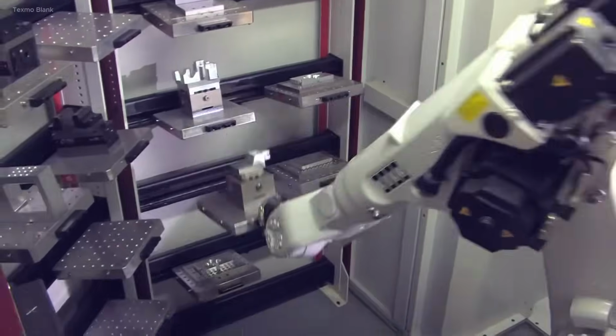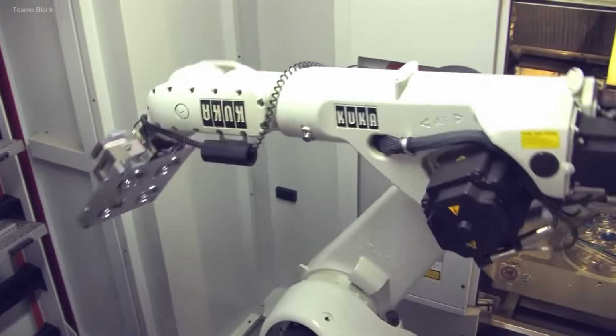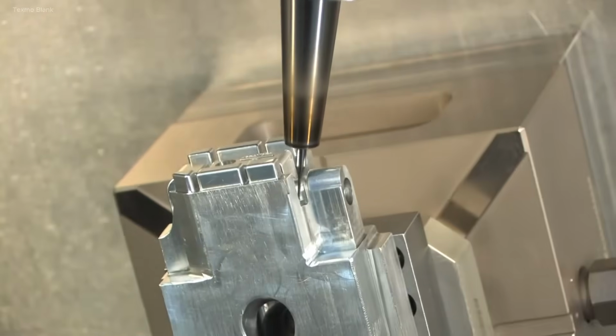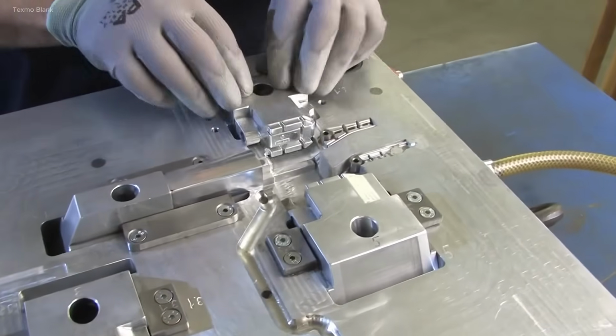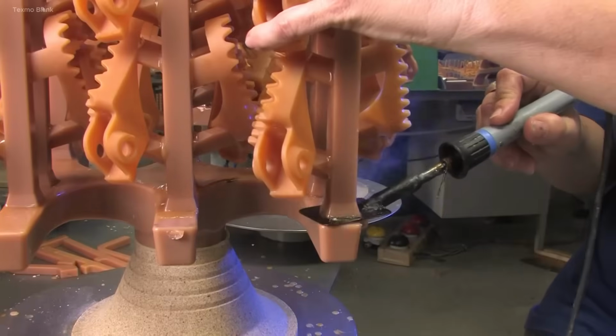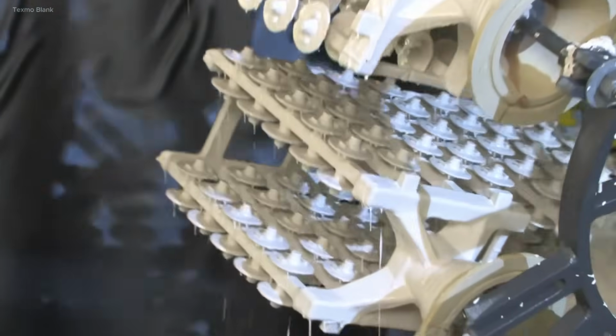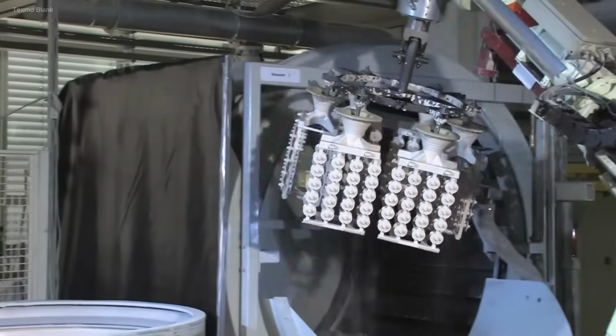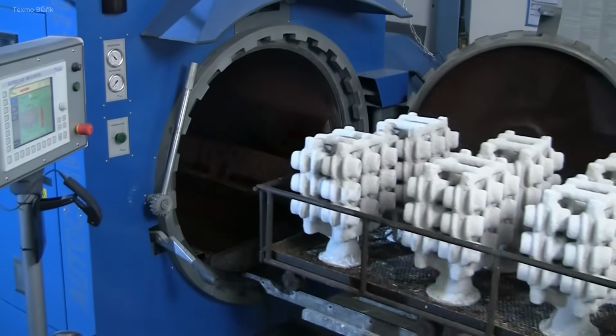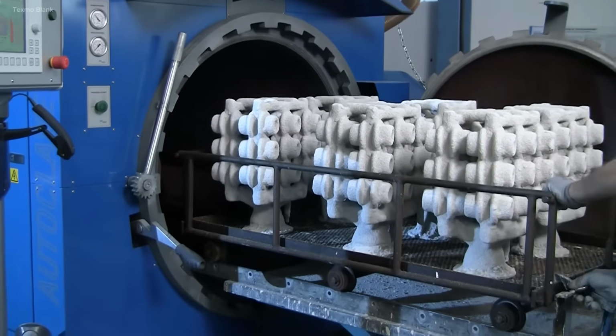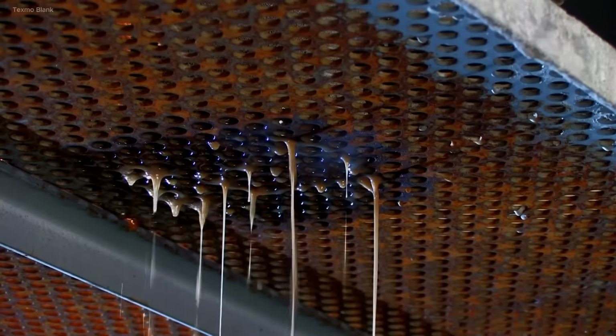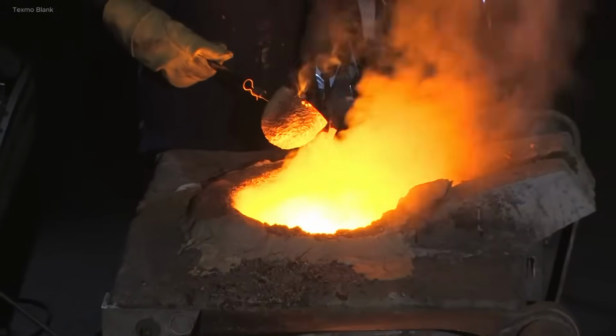The investment casting process begins with engineers developing a suitable tool based on order drawings or 3D data. In the wax room, aluminum or steel injection tools are used to produce wax parts, which are assembled into tree clusters. These are repeatedly dipped in ceramic slurry and coated with sand about 10 times to form a stable ceramic shell. The wax is then melted out and recycled. The ceramic shell is fired at over 1,000 degrees Celsius to prepare for casting.